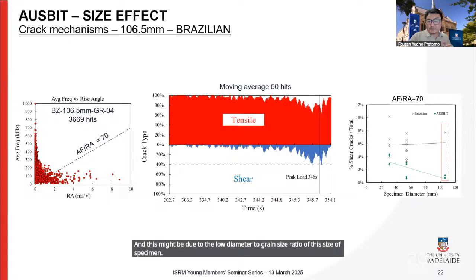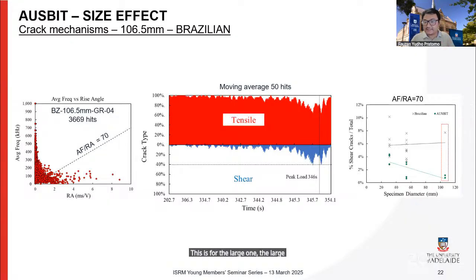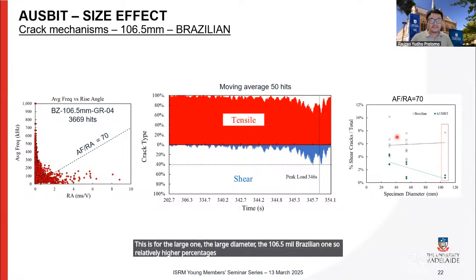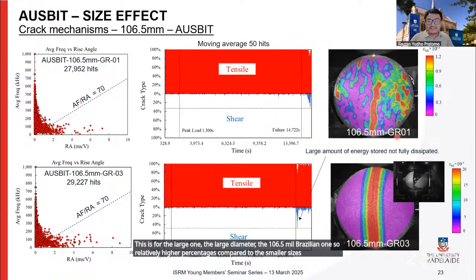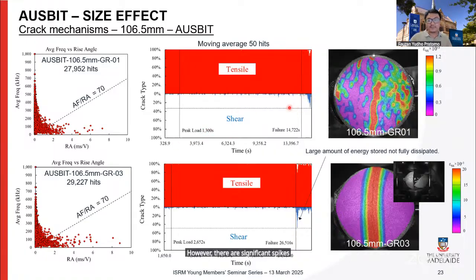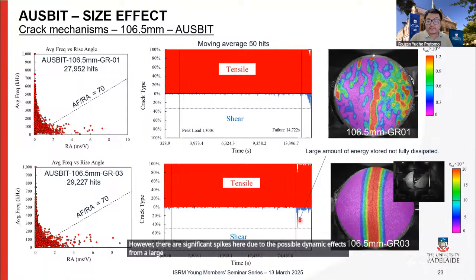This is for the large one, the large diameter, the 106.5 mm Brazilian one. So relatively higher percentages compared to the smaller sizes. Well, this is under AUSBIT, so indicating that in the controlled failure, the shear cracks decrease with size. However, there are significant spikes here due to possible dynamic effects from a large amount of energy being stored and not being fully dissipated because of the size limitation of the AUSBIT.